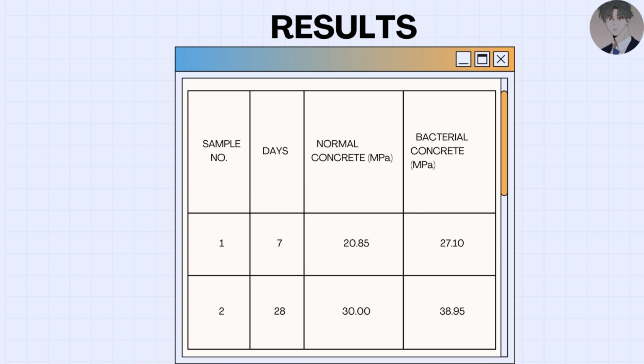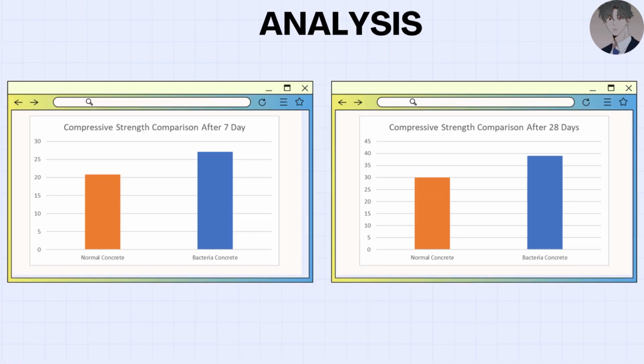27.10 megapascal for compressive strength. And sample number 2, we tested on day 28. For normal concrete, we obtain the compressive strength of 30.0 megapascal. As for bacterial concrete, we obtain 38.95 megapascal in compressive strength for day 28.